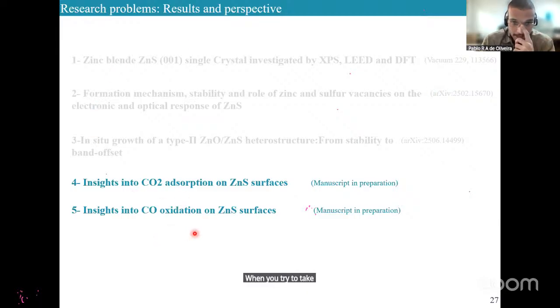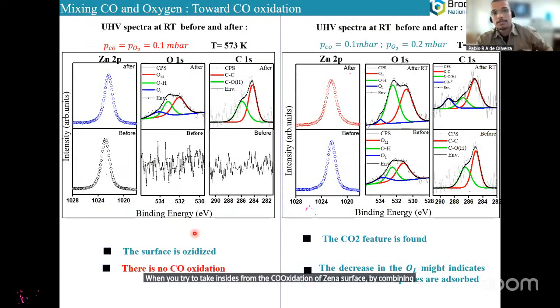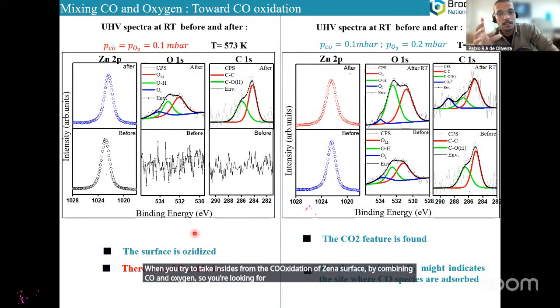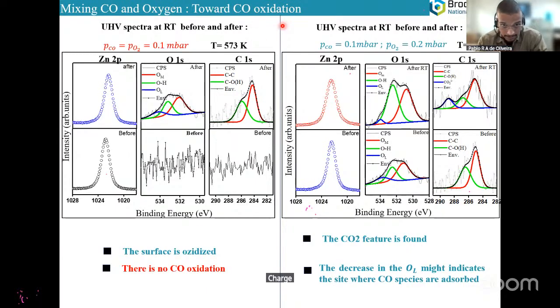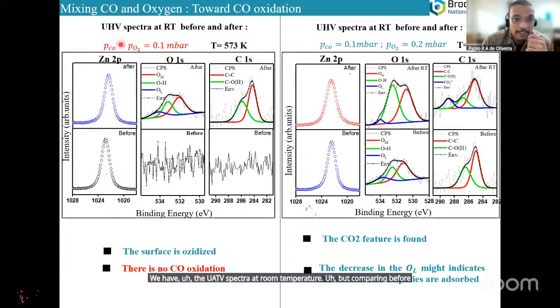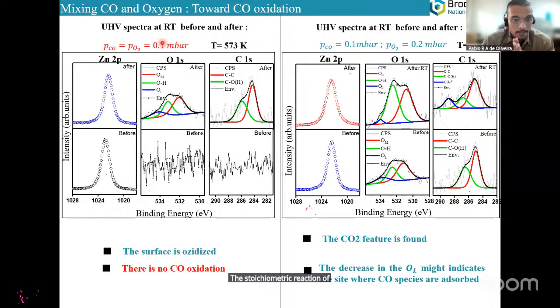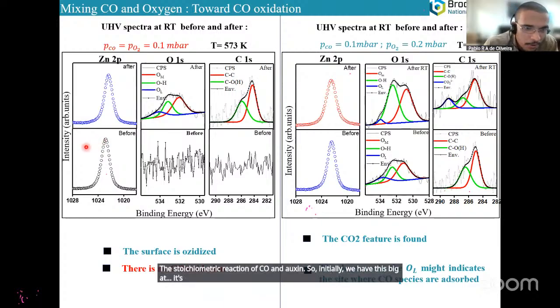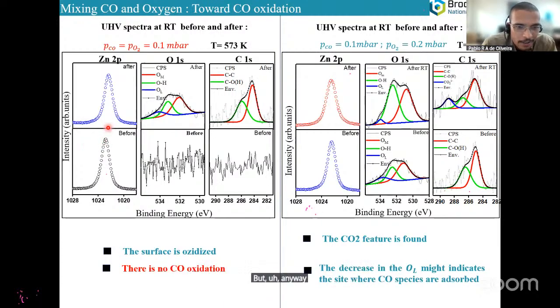So that's why we would move to the last part, where we try to gain insight into the CO oxidation of the ZnS surface by combining CO and oxygen. So we are looking toward CO oxidation. In the left panel here, we have the UHV spectra at room temperature, comparing before and after the stoichiometric reaction of CO and oxygen. Initially, we have this peak, it's not marked here, I don't know why, but anyway, it's around 1022.8, and this peak is slightly shifted toward low binding energy.